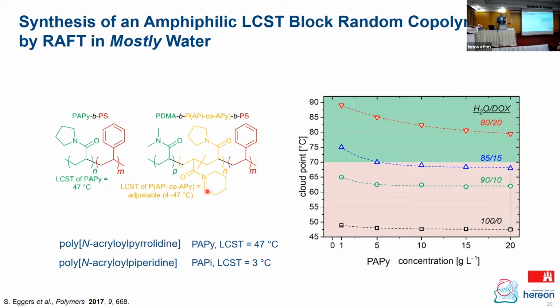The cloud point, the LCST, of the corresponding homopolymers is quite different. In the first case with the 5-membered rings, we have an LCST around 50 degrees centigrade. And in the other case with the 6-membered rings, we are very close to the freezing point of water, around 3 degrees centigrade. So that gives us a huge range. And of course, I will come back to that, we can adjust the LCST by copolymerization of these two different monomers, but that comes in a minute.